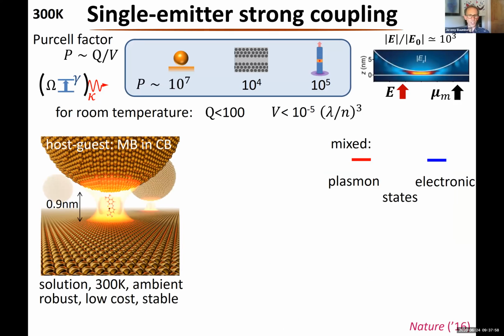So what we did in this system is that we used a sort of scaffolding system. Because dye molecules, anything which has got an extended conjugated system, tends to want to lie flat. Any ring system tends to want to lie flat on the gold, just as we were talking about for the 2D systems, the graphene and everything like that. Most of the dipoles in those systems are in plane, so they're not really good to couple into this system because the fields need the dipoles vertical. So what you have to do is make it stand up. What we did was we used a molecule called cucurbituril, which allows us to scaffold the dyes vertically.